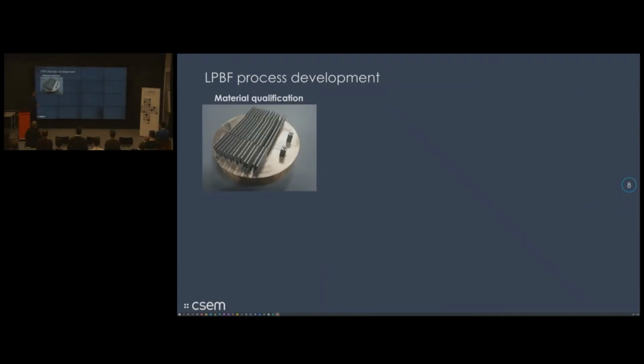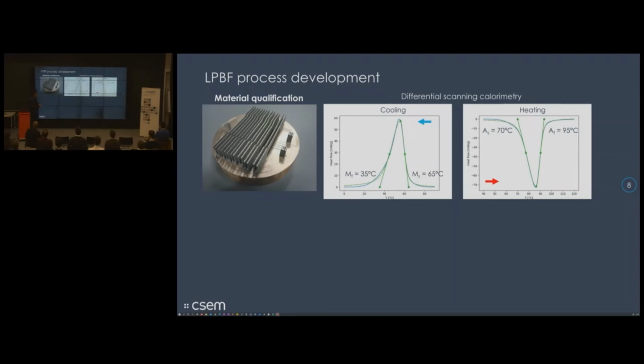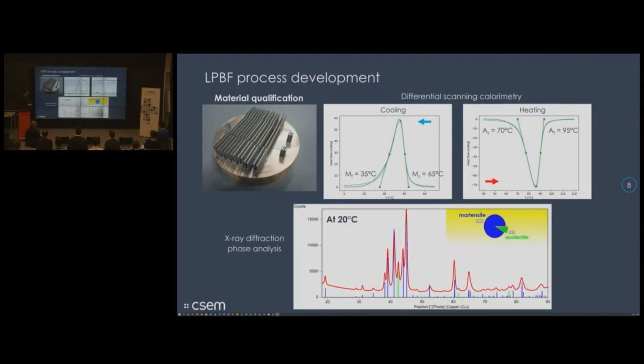Then we did material qualification of the optimal parameters for laser powder bed fusion. We did differential scanning calorimetry in order to measure the transformation temperatures. So the martensite finish was 35 degrees and austenite start 70 degrees. You can see that it's already slightly higher. This is usually the case because there is a different rate of, let's say, evaporation of nickel and titanium. So by changing, if you have a very high power, you can shift towards higher transformation temperatures when you have a material that starts at lower temperatures. And we did also phase analysis. So at room temperature, we have more than 90% of martensite in the as-built nickel titanium parts.